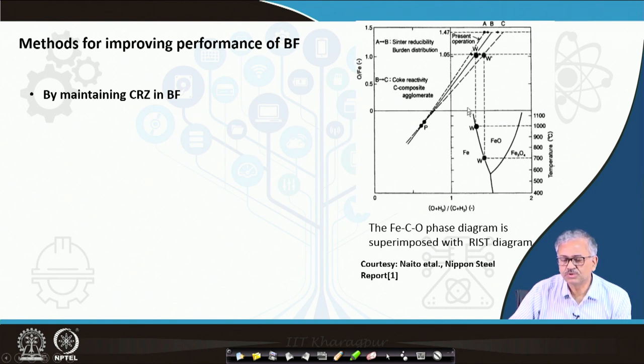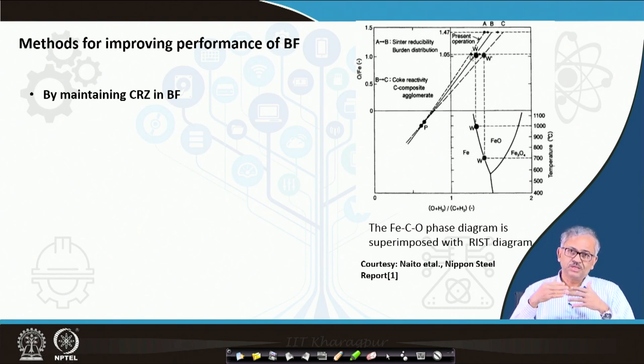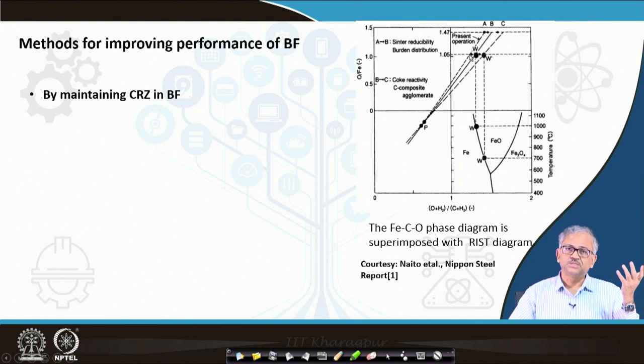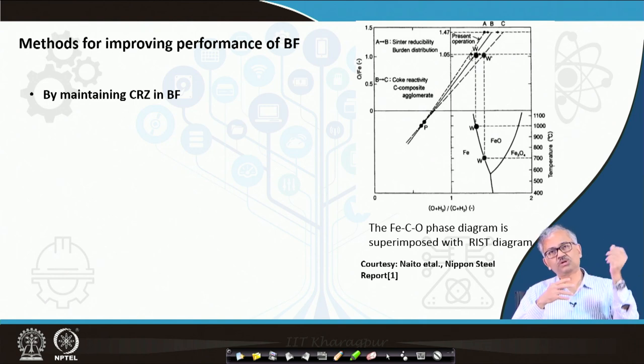O/C lower means your CO percentage in the gas is higher. The equilibrium O/C from A to B is at one value, and the actual O/C is lower — meaning you have more CO in the gas than the equilibrium requirement. In the actual blast furnace, CO may be 80% — more than the 70% equilibrium value at 900°C — so CO utilization will be further lower.